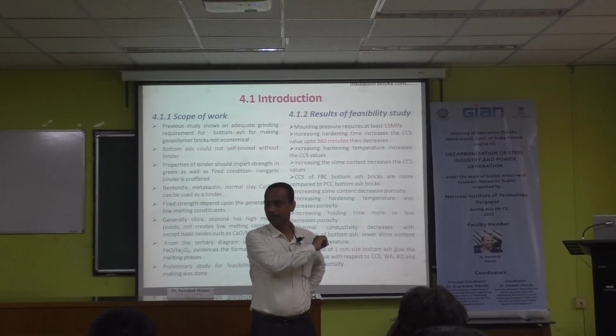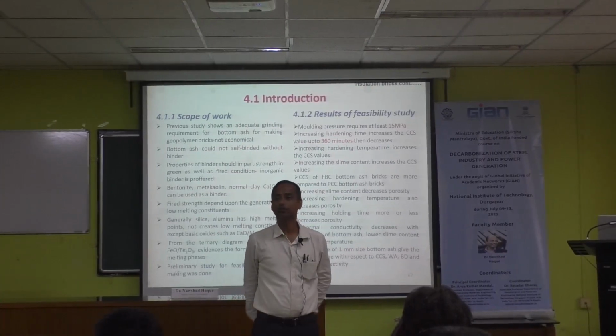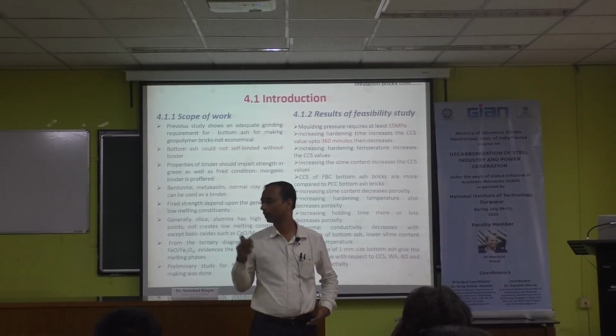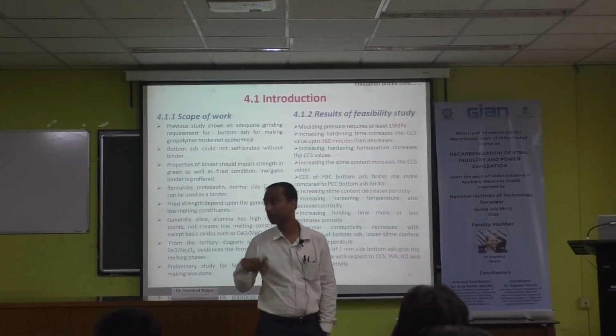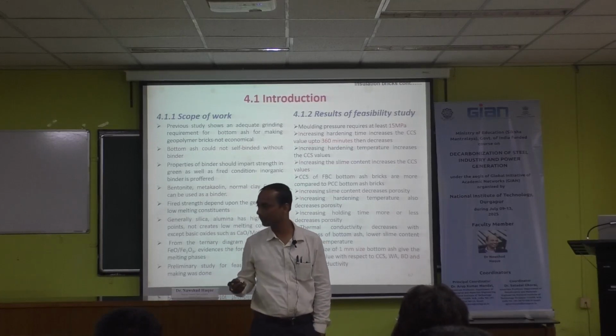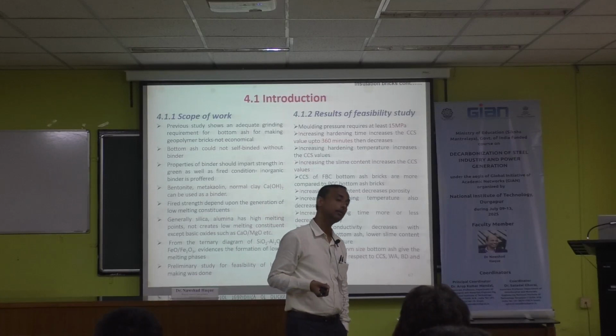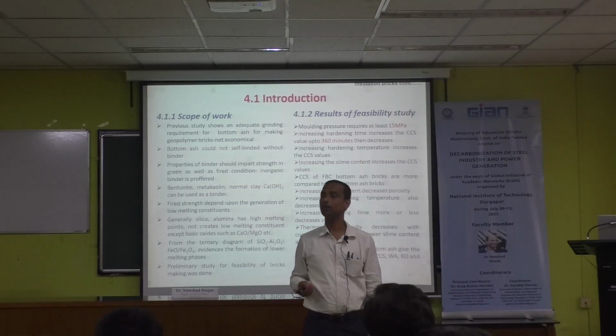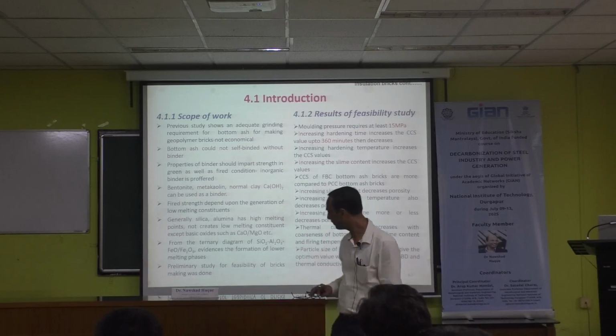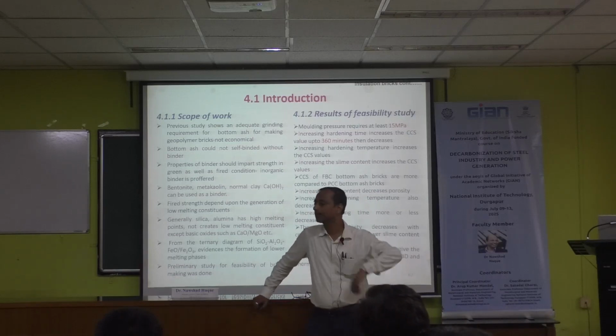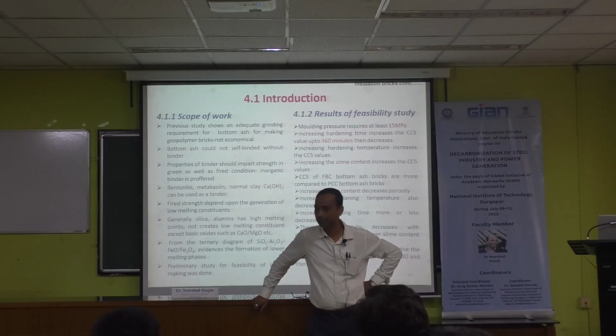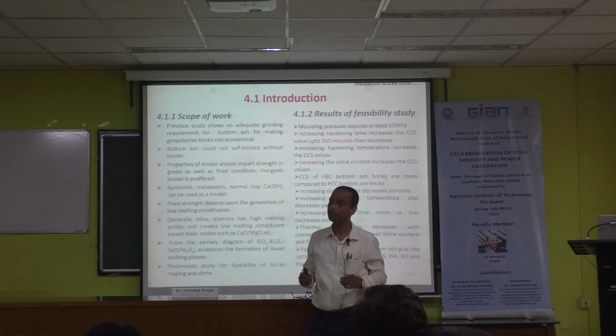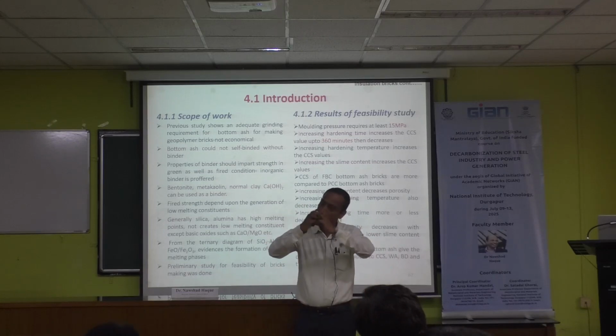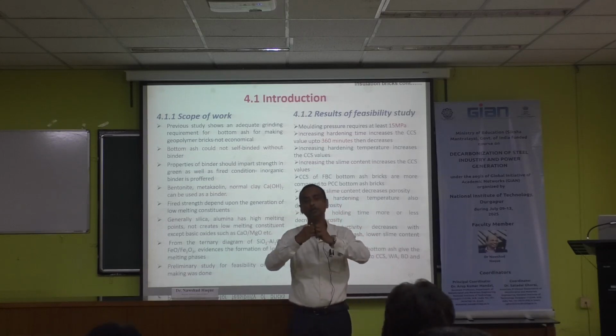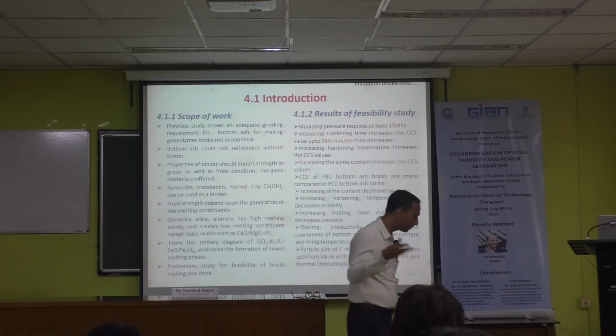In case of geopolymerization, we did not get so much strength due to the pores in the bottom ash. It requires fineness and grinding, which is energy consuming, to make the geopolymer. But we can make construction things. Then we tried iron ore slime addition as a binder. Both are coarse materials, so interparticle space will be there. If we add a binder which will accumulate the coarser particles, then it will give the solution. That was our idea at that time.